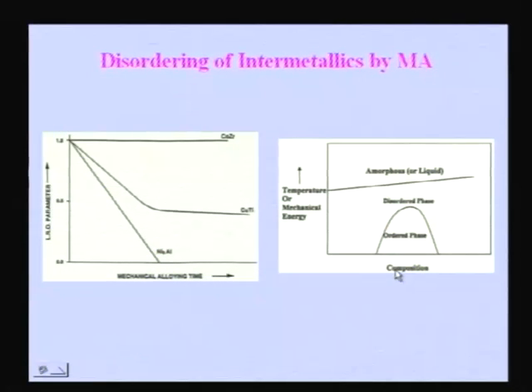Similarly, if you look at an ordered phase and start increasing the temperature, we know usually there is a temperature at which it becomes disordered, and if you start increasing the temperature further, it becomes liquid, isn't it? Sometimes in some kinds of compounds this disordering temperature and the melting point might overlap with each other. In case of copper zinc kind of beta brass, there is a difference in this temperature, because the melting point is different, the disordering temperature is different. So, similarly here there is an analogy between the temperature and mechanical energy. If you keep on increasing the mechanical energy, the ordered phase becomes disordered, and this disordered phase, if you keep on increasing the mechanical energy further, becomes amorphous, which is similar to the liquid. So, this is similar to what happens if you keep on increasing the temperature. An ordered phase becomes disordered and becomes liquid. So, instead of liquid, with mechanical energy it becomes amorphous.